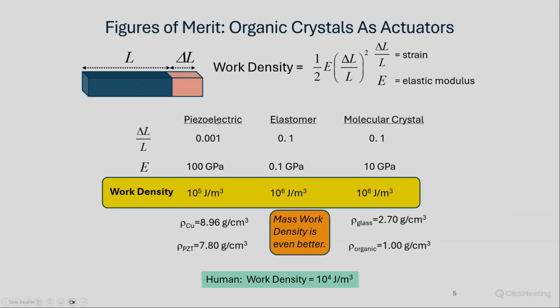And then you can use different classes of materials, piezoelectric, polymer elastomers, and then molecular crystals that we like, and plug in typical values for the strain, delta L over L, and the elastic modulus E. And what you can see is that molecular crystals have a sweet spot where they have a relatively high strain, but they also have a relatively high elastic modulus. And that combination says that the potential work density contained within a molecular crystal that undergoes some deformation, some strain, some length increase, is on the order of 10 to the 8 joules per meter cubed.